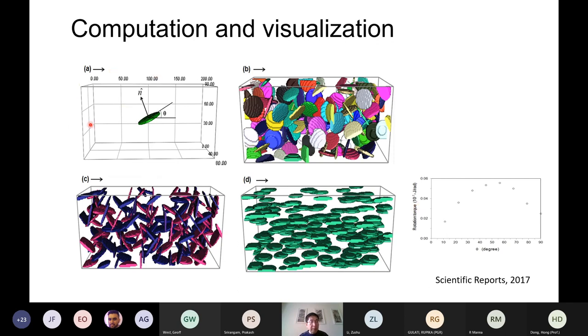In that case, we actually calculate whether electric current can be used to align the inclusions, to align the phases. Suppose we put graphite flakes into salt water. The flakes will have their directions in various ways like this. If we apply electric current, can they actually align? We find yes, it can, and it will generate a very big torque force to align those flakes into a certain way, which can be used to make more functional materials.